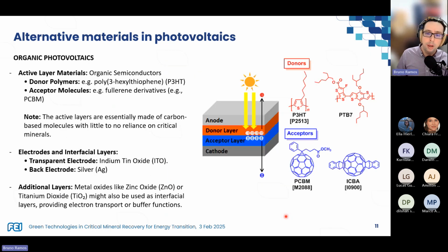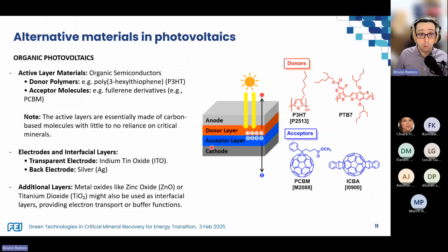So in terms of organic photovoltaics, what changes here is that the absorbing layer is actually composed of two parts, the donor and acceptor layers. And we normally use organic semiconductors like P3HT, this one shown here, and acceptor molecules, which are normally based on fullerene. Fullerene, if you are like us Brazilians who like soccer, is like the soccer ball carbon molecule with 60 or more carbons. We have these fullerenes here. They have a very well-distributed electron field, which makes them very good semiconductors.